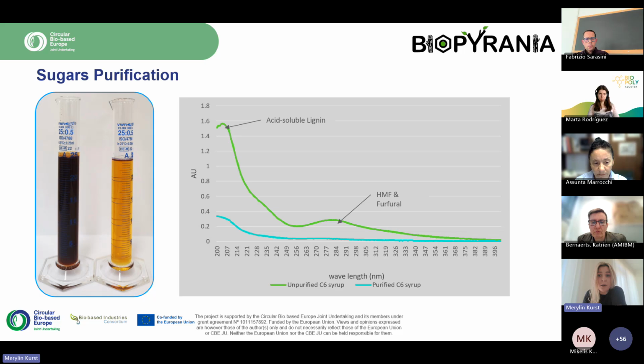Sugars can be further purified, like I told, because they still contain impurities such as lignin, HMF, furfural, organic acids. From the image and graph, it can be observed that sugars obtained from our standard process appear as a dark brown syrup and contain dissolved acid-soluble lignin, HMF, and furfural. After the purification step, both the color intensity and impurity levels are significantly reduced, like shown in the graph, where the green line is unpurified C6 syrup and the blue line is purified C6.